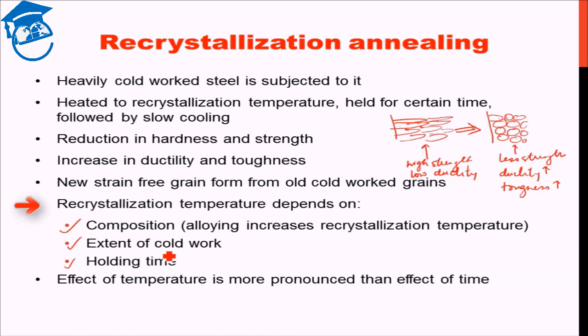If we want recrystallization to happen quickly, we would have the temperature high. Between time and temperature, temperature has a much more pronounced effect on recrystallization rate than time. A marginal increase in temperature leads to a drastically large decrease in the amount of time required for recrystallization.